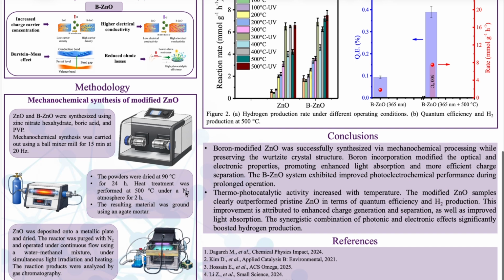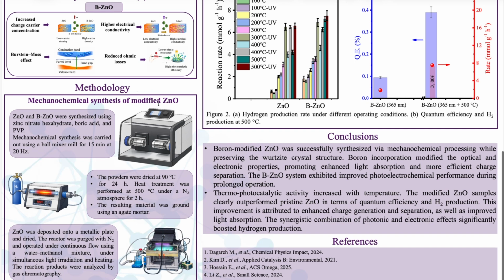Methodology. To synthesize the materials, we employed a mechanochemical synthesis method. Both pure ZnO and boron-modified ZnO were prepared using zinc nitrate hexahydrate, boric acid, and polyvinyl pyrrolidone, or PVP, as precursor materials. The mechanochemical synthesis was carried out in a ball mixer mill operated for 15 minutes at 20 Hz. The resulting powders were then dried at 90 degrees Celsius for 24 hours. After drying, the samples were heat treated at 500 degrees Celsius under a nitrogen atmosphere for 2 hours. Finally, the synthesized material was ground using an agate mortar.